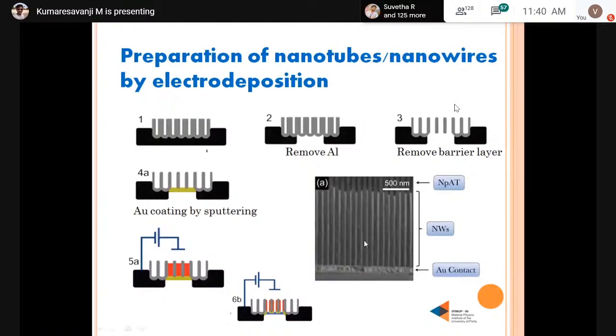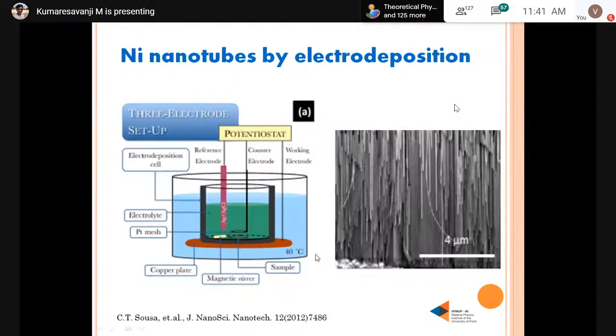Okay. By changing the electrodeposition conditions like timing, electrolyte molarity or pH value, we can control whether it is nanotubes or nanowires, and we can also change the thickness of the nanotube walls. This is the setup used in our lab to prepare the nanotubes. Here I show the nickel nanotube preparation and micrographs of the same.